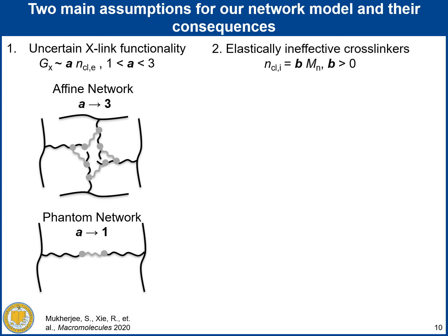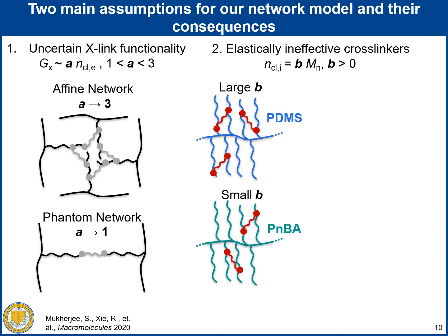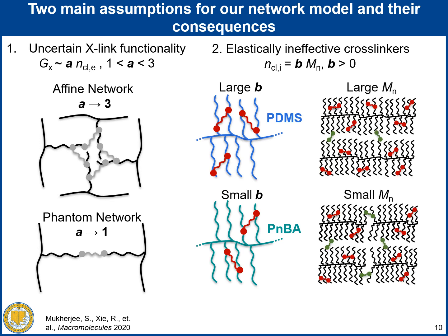Secondly, we assume that the number of elastically ineffective crosslinkers is proportional to the molar mass of the Bottlebrush polymer. The proportionality constant B represents the number of intra-Bottlebrush crosslinkers per unit molar mass of a Bottlebrush polymer. And this value B should only depend on the specific combination of polymer and crosslinker. Given the same total number of added crosslinkers per unit volume, the smaller molar mass of Bottlebrush polymer should lead to a greater probability of inter-Bottlebrush elastically effective crosslinks.